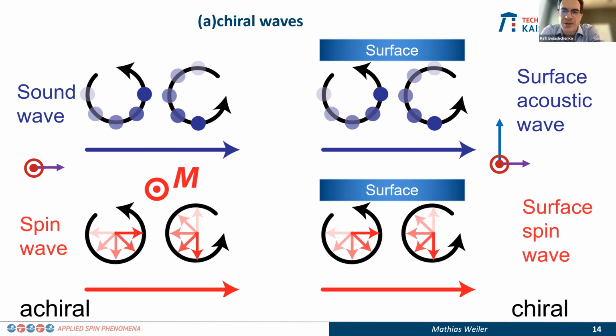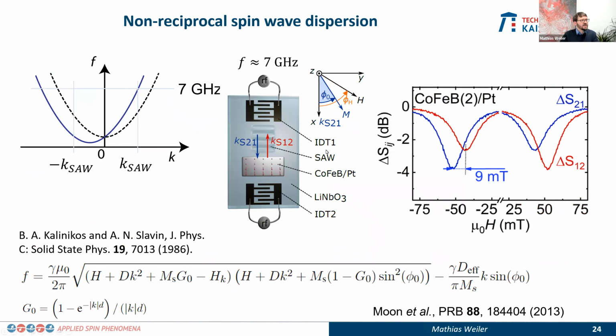Thank you. Let me ask a question. So is it possible to do some sort of gating to tune the frequency of those waves or coupling to magnetism, perhaps by tuning the DMI, and make the devices that you were discussing tunable? So I'm not aware of actual experiments that have shown that. What has been shown experimentally is that you can tune the Dzyaloshinskii-Moriya interaction either by strain or by electric fields, right? In similar thin film bilayers. So that means you would basically expect that you can tune this non-reciprocity in the resonance field by gating, right? Okay. I see a bit of the problem with doing that with the DMI, that they basically have very large line widths, and you tune it a bit.